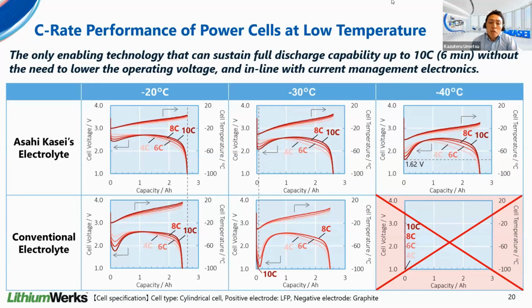Energy type cells were evaluated, but power type cells were also evaluated. Low temperature performance of LFP graphite 26650 cylindrical cells was tested from minus 20 to minus 40 degrees C. The graphs above show the result of acetonitrile, and below for the standard carbonate electrolyte. Each graph shows the discharge curves and the heating behavior of the batteries. It can be seen that the acetonitrile-containing electrolyte suppresses the voltage drop and internal heat generation of the batteries. In addition, while standard carbonate electrolyte was not able to discharge at minus 40 degrees C, acetonitrile made this possible.